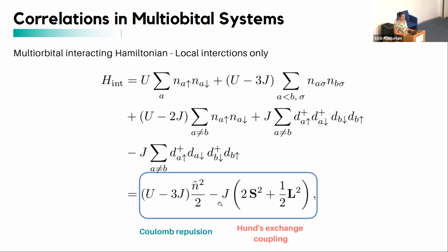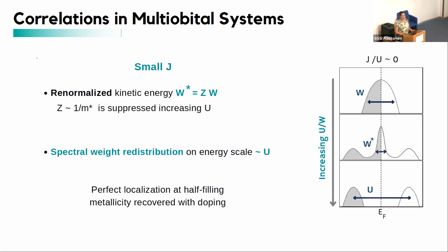So let me start with a case in which I put J almost 0. So essentially I have a collection of multi-orbital correlated systems, but the behavior is pretty similar to the standard Mott insulator transition. So you start with a small U, in which you have a well-defined density of states for a metallic state. So it's coherent around the Fermi level. If now I increase U, the other important value is the kinetic energy of the system, so the hopping value. And I'm using here as a measure of the kinetic energy the bandwidth W.